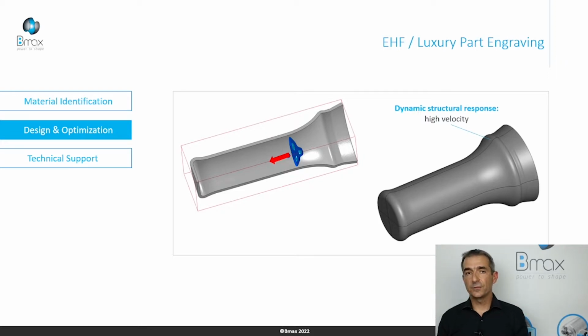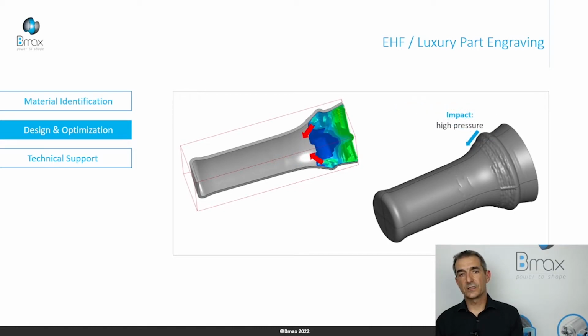So at this time, we have a pressure wave, an incident pressure wave, which comes from the electrode system into the sample and creates a dynamic structural response. We have just an initial velocity on the top of the sample. We have no large displacement and deformation. By this velocity, we create an impact, and we start the engraving of the sample. And we generate in water a very high pressure. The colors show the magnitude of pressure, from 1,000 to 6,000 bar.